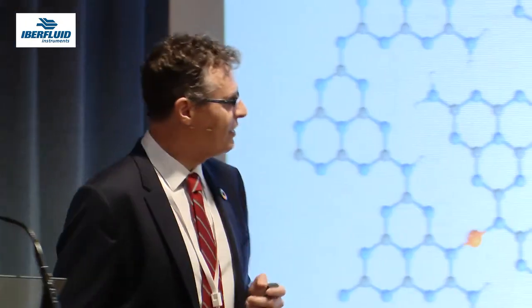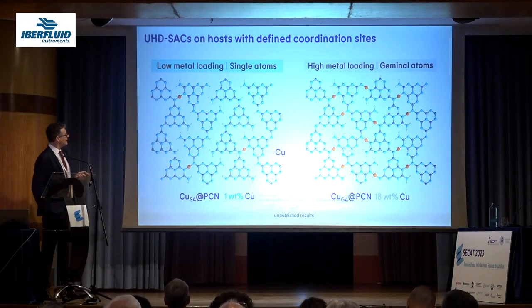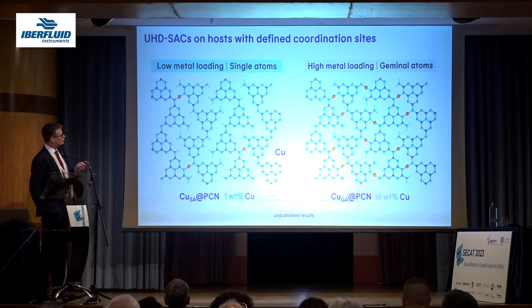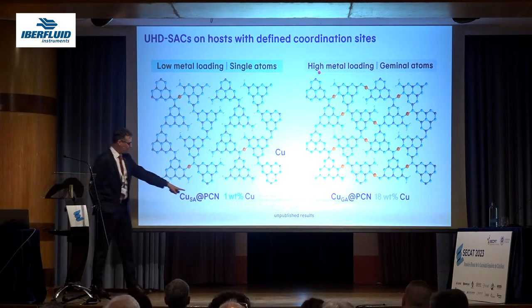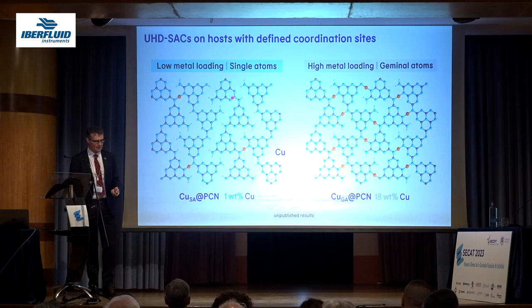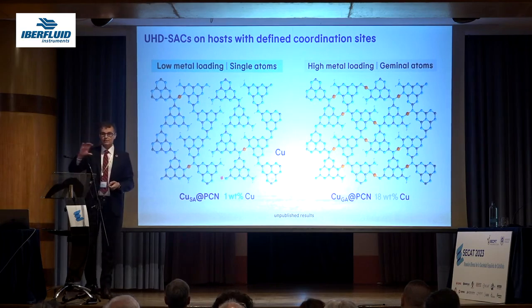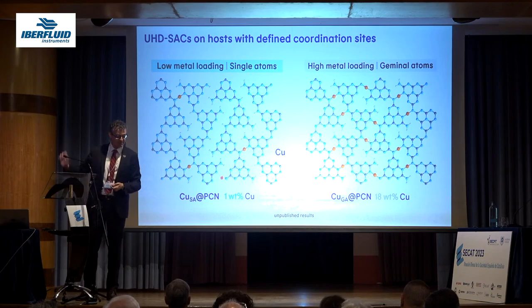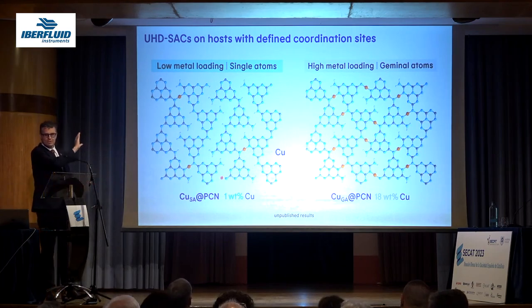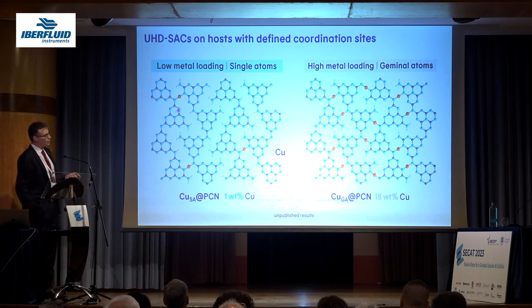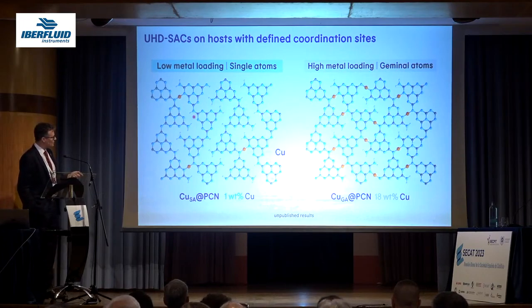And so what we thought is that, wait a second. If we have supports, hosts, with well-defined coordination sites, like what you see here, this is a polymeric carbon nitride, here, PCN. What you could do if you could now vary the loading, and I told you that you could make high loadings of these metals, what you could do is these two extreme scenarios. So on the left, you will have a low metal loading, and then on the right, you will have high metal loadings. And what you basically do is condensing, saturating all the sites that you have to put single atoms, which are this metal center here, this metal center here.